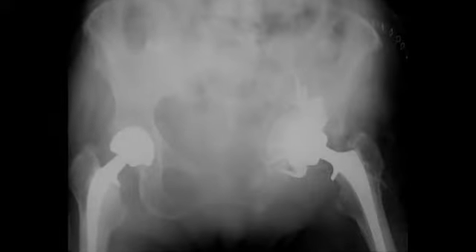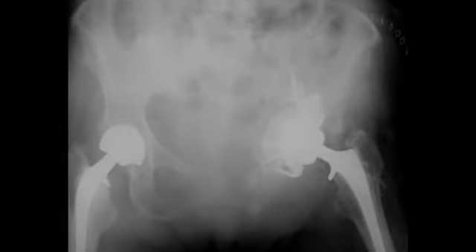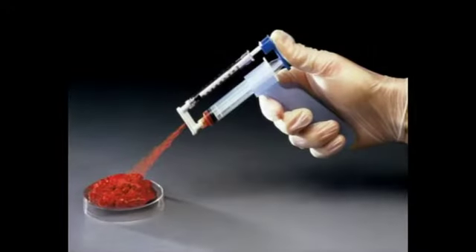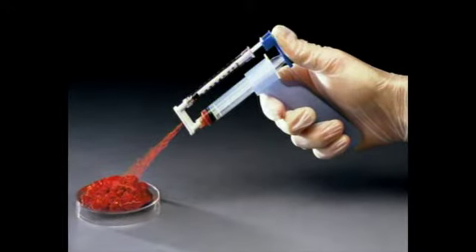A thin titanium screen was molded and placed within the former floor of the acetabulum. 40 cc's of Conduit tricalcium phosphate, TCP, granules was clotted with platelet-rich plasma prepared by the Symphony PCS device. The clotted Conduit graft was molded into a patty and placed within the confines of the acetabular protrusio fracture defect. A 54 millimeter revision acetabular shell was impacted in place and secured.